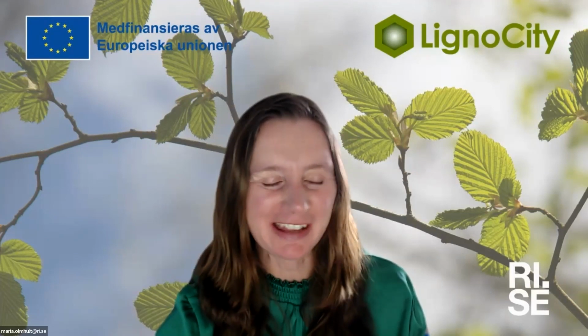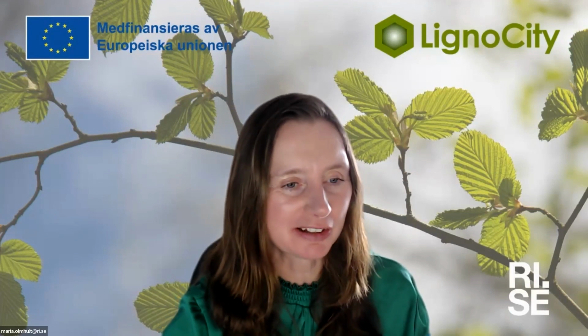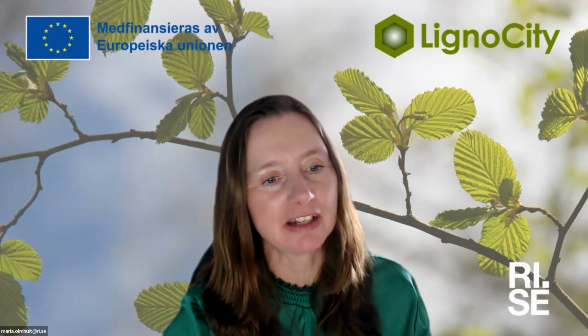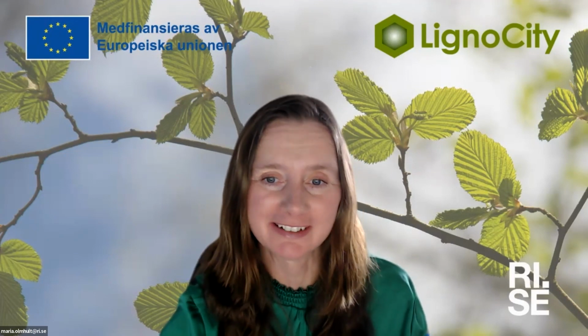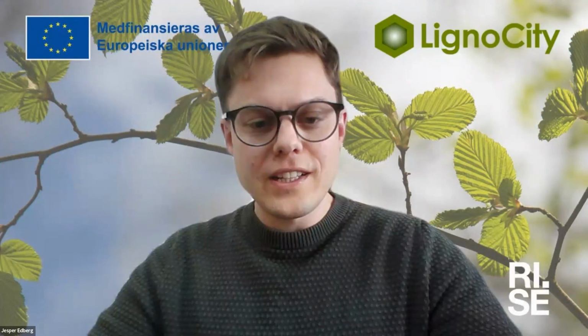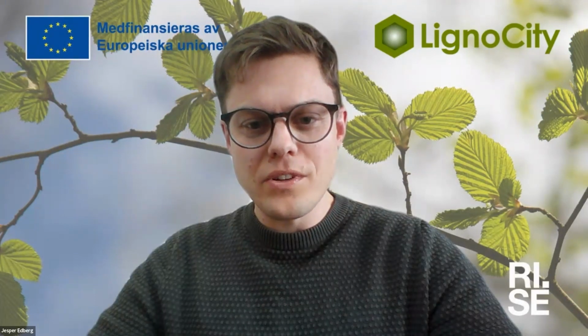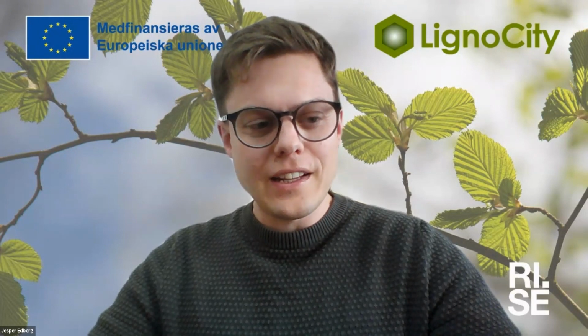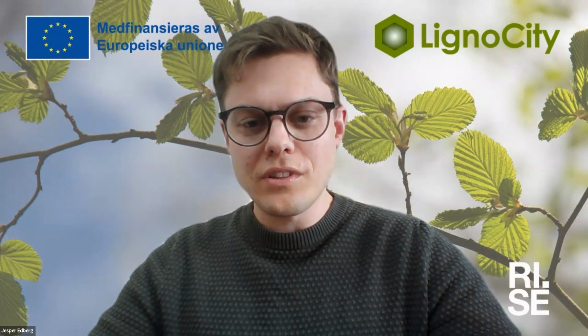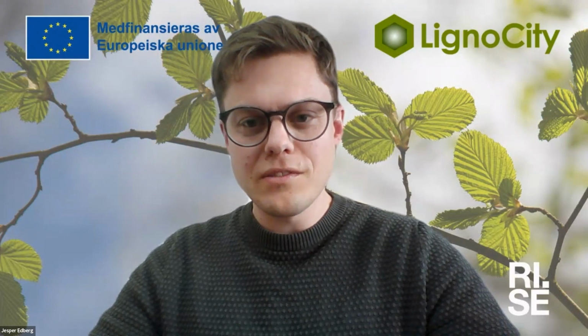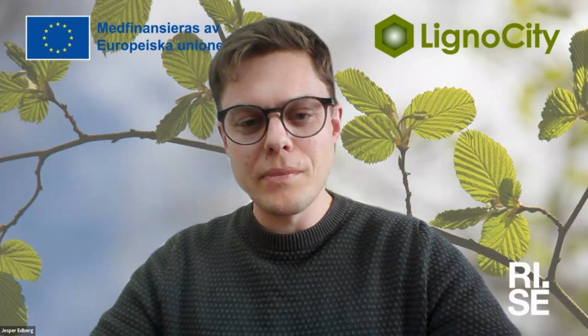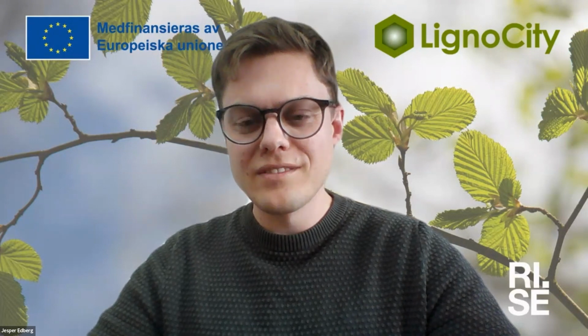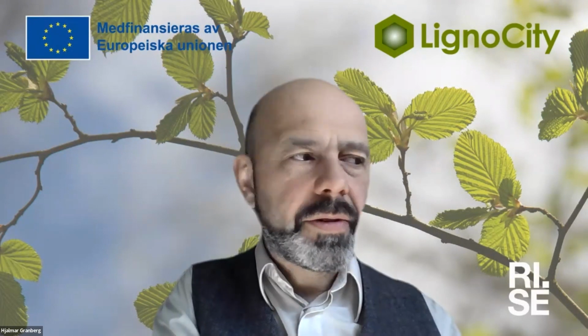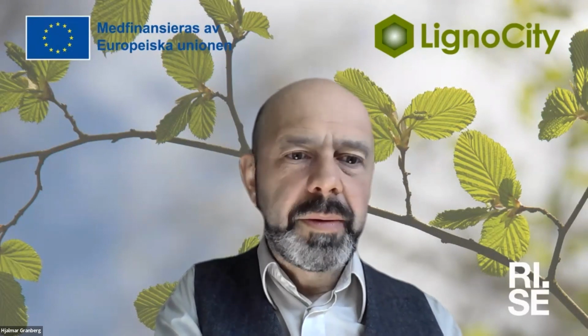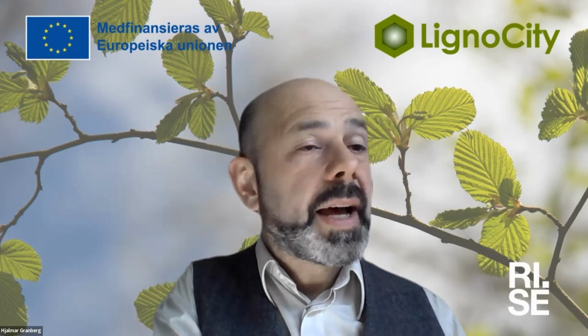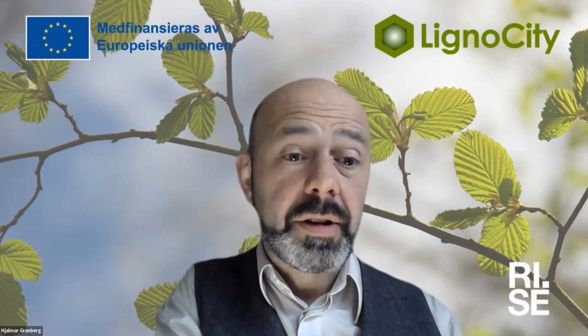Congratulations. And the last question that went together was, does it depend on the nature of the lignin or the power of the laser? So power of the laser, definitely. We have seen higher laser power, higher conductivity, but at some point you start to get cracks in the film, which is probably because of these volatiles. So we haven't really been able to push the technique to its maximum, I don't think. Yes, and we are trying also to use charring materials, other catalysts that can help the conversion as well.